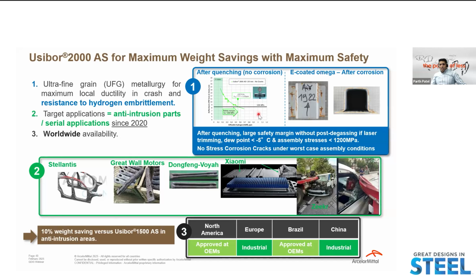There's a perception, or myth, in the industry that Usibor 2000, since it has high strength, will have hydrogen embrittlement issues. Actually it's less susceptible to hydrogen - it's a myth. People assume there's a problem with the material, but there are no hydrogen embrittlement issues.